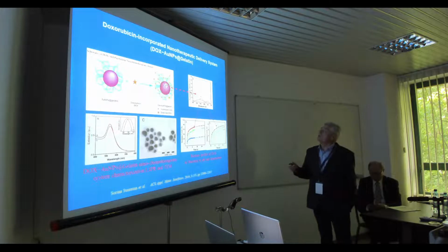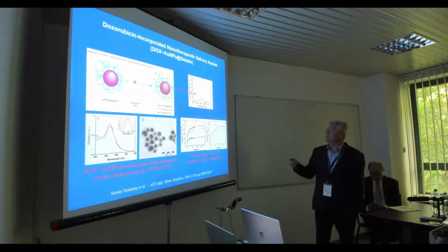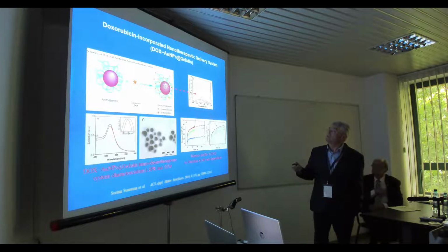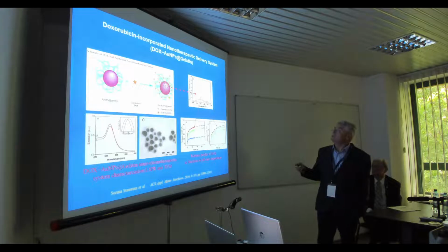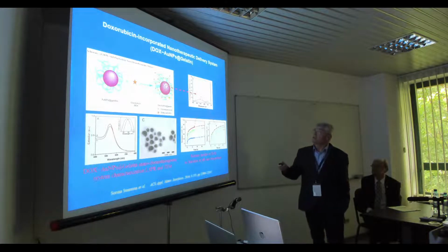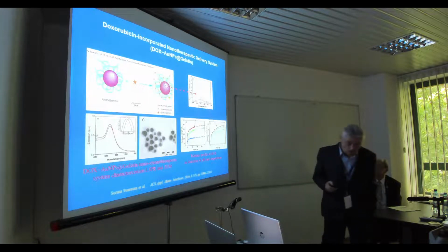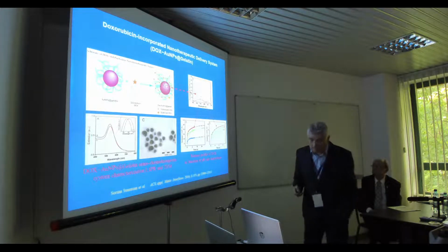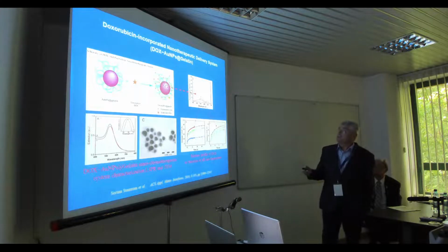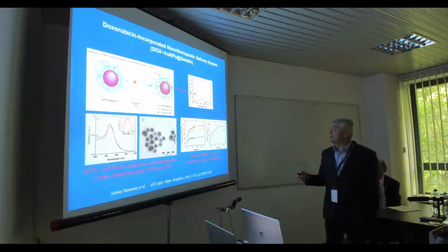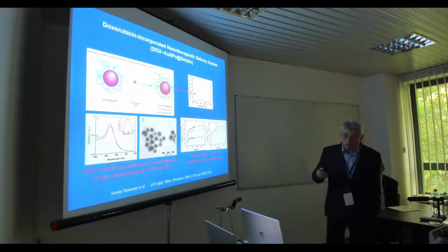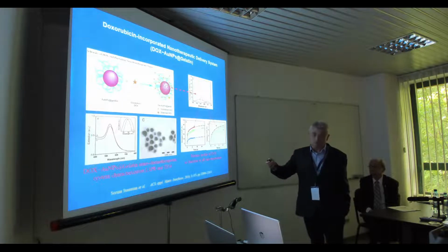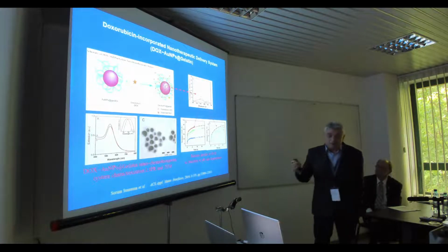You can notice then, when you measure at the same concentration, the fluorescence spectrum from the free doxorubicin and the doxorubicin captured on the gelatin shell. There is some decrease in intensity, which is usual. But what is more interesting, we did a study of delivery, because it's not enough only to load the nanoparticle with the drug, it's very important to deliver.